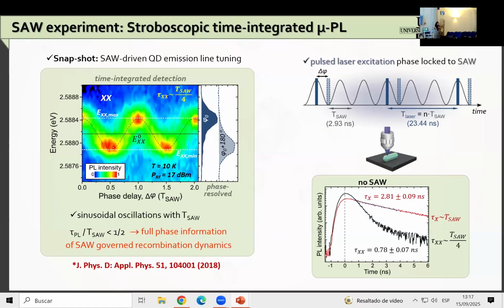The same occurs with the flakes, because when you disperse the flakes, it's very difficult to disperse them so they are completely individual and very well oriented. So the coupling is also random. But the best way to achieve the maximum coupling of the entire system is by encapsulation into some piezoelectric but transparent material. And just to go back to your previous question, in this case, we designed the conditions of the MBE growth so that we can obtain such a structure. But it doesn't have to be like that. One can use different parameters during the epitaxial growth, so we can have nanowires which, for example, have a flat top profile. So this really depends on the design and the parameters we use. That's a study on its own.